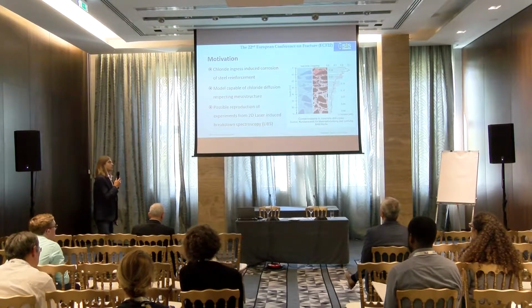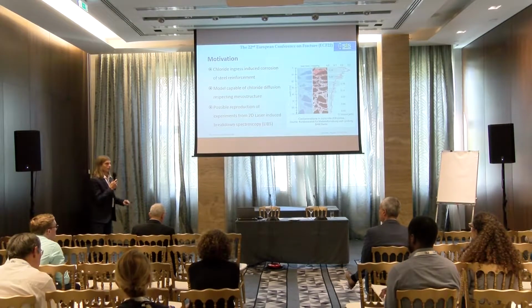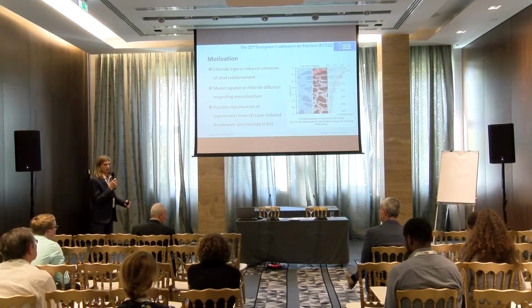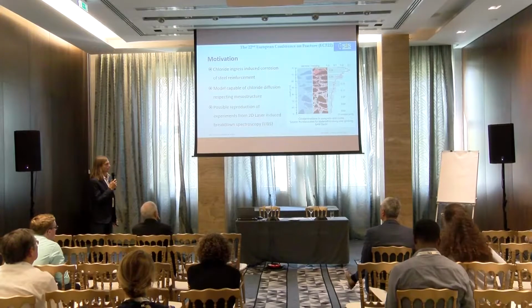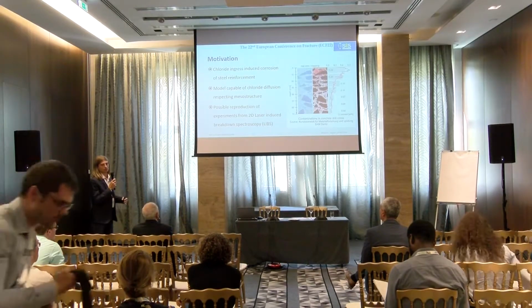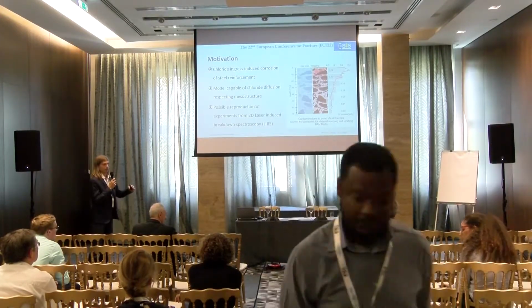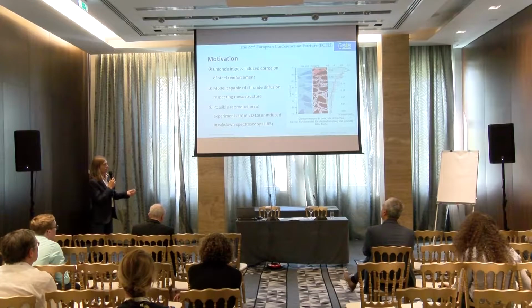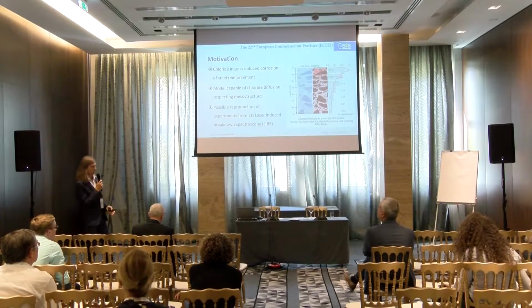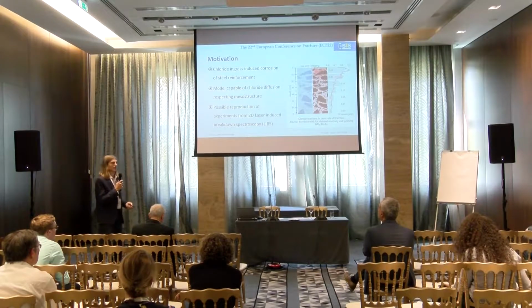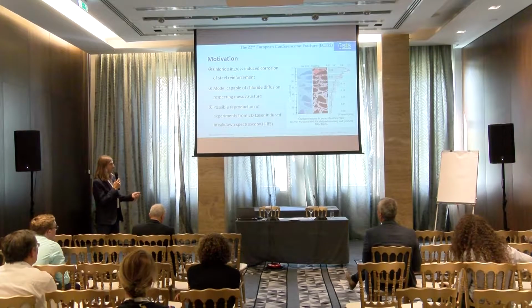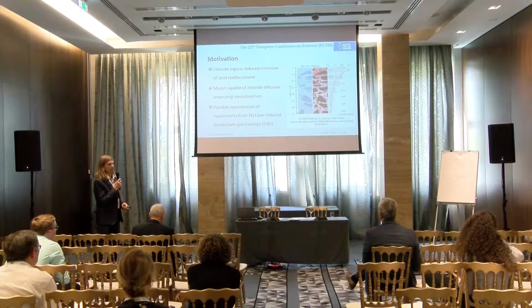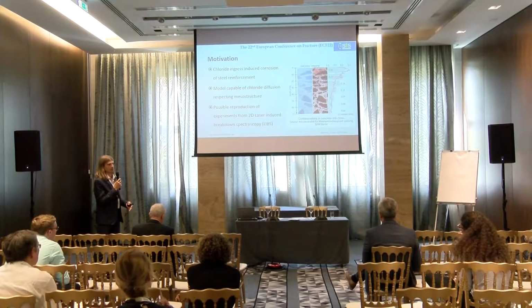The motivation behind the work is modeling and the analysis of the chloride ingress into the concrete. And this has an impact on the durability of the concrete because of the corrosion induced by the chlorides from de-icing agents penetrating to the level of the reinforcement. And there are several approaches to analyze the effect of chlorides. And currently there is an availability to analyze even 2D profile of the chloride content in the concrete via laser-induced breakdown spectroscopy.